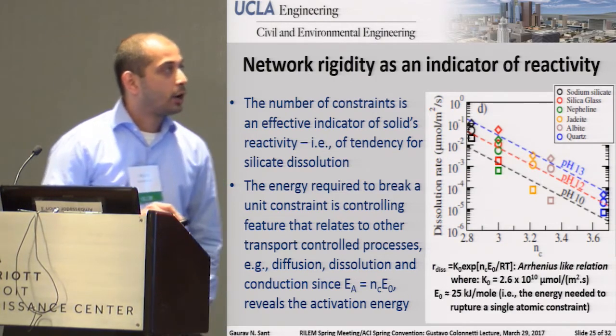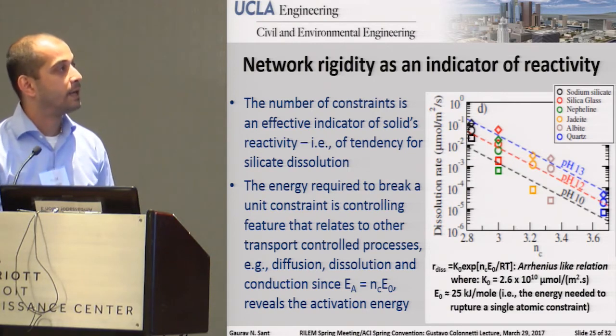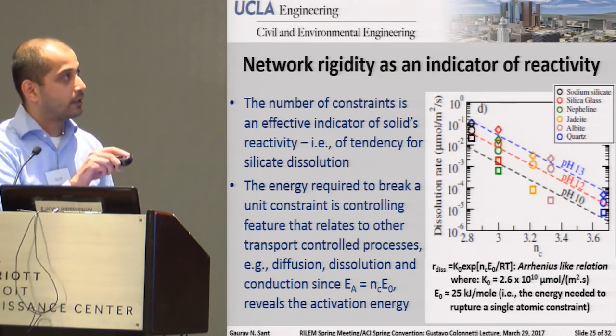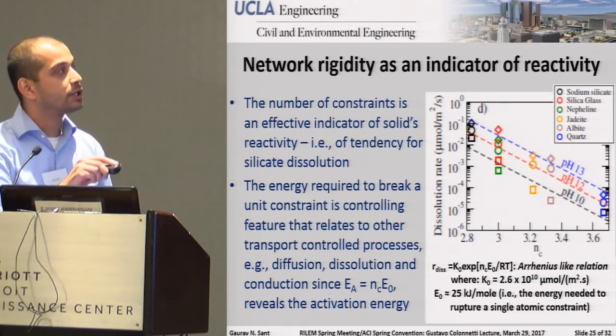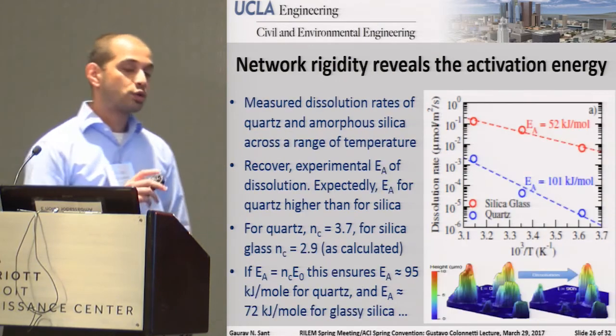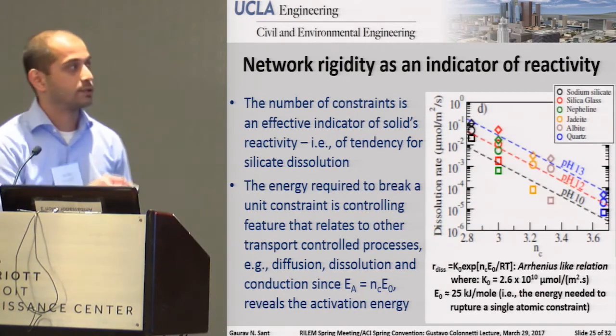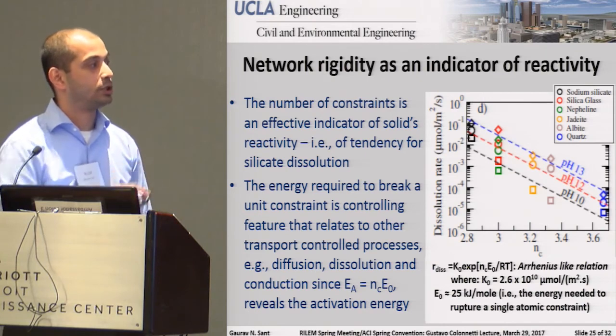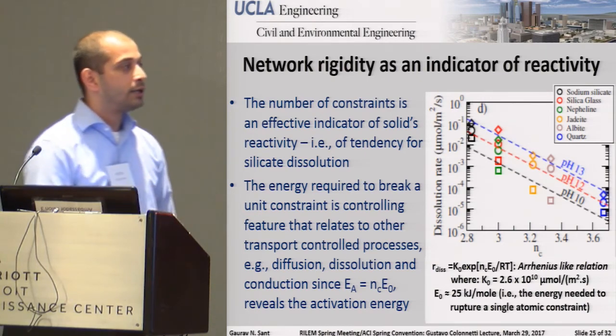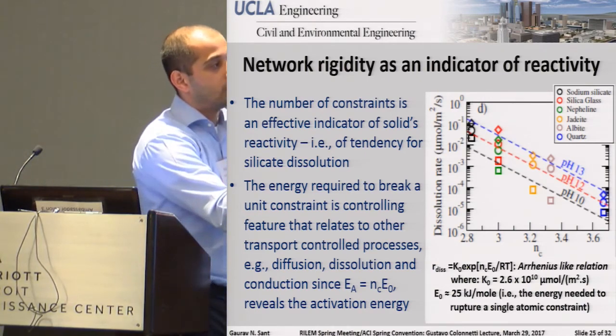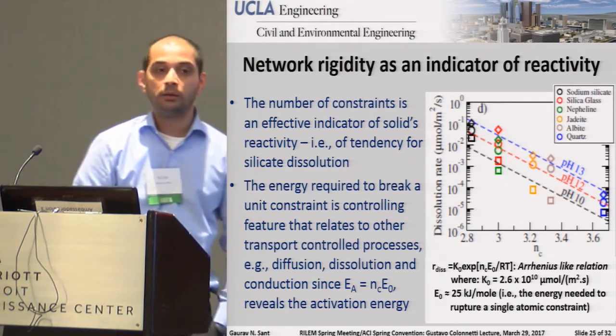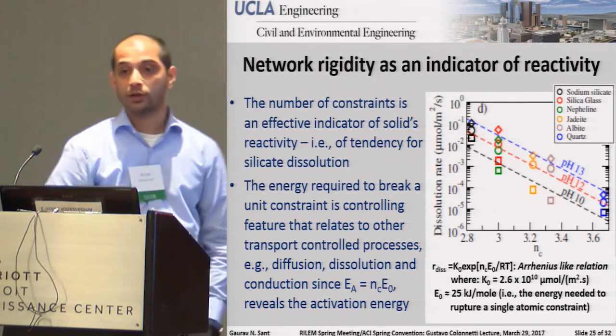Now, an important thing to point out, which is related to this, and I'll come back to this in a second, is I'll make the case that the energy required to break a unit constraint is also related to other features, to other processes, specifically things like diffusion, dissolution, and conduction. But an important thing that you can start to tell very quickly is if you consider an Arrhenius-like relation, this term up here, NC times E-naught, basically reveals the activation energy of the process.